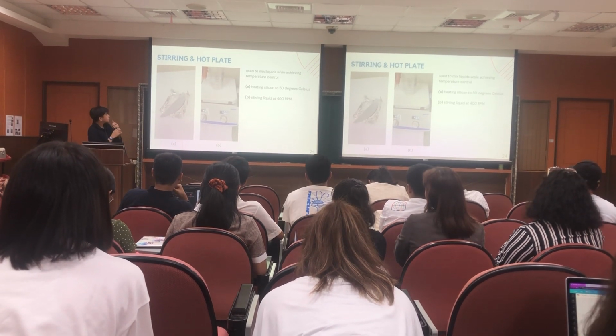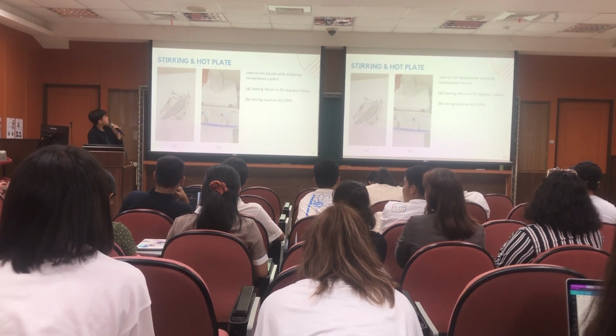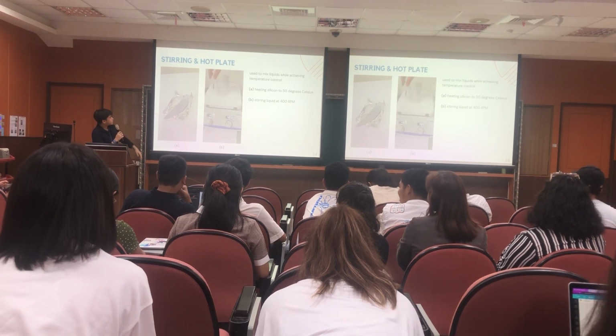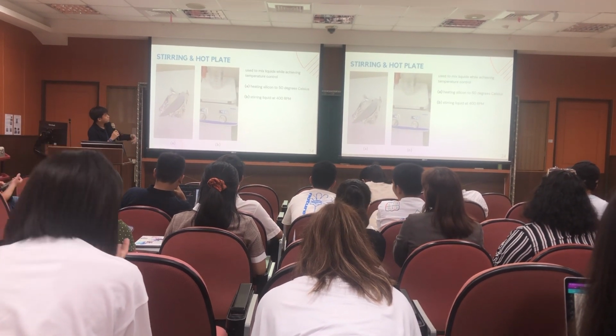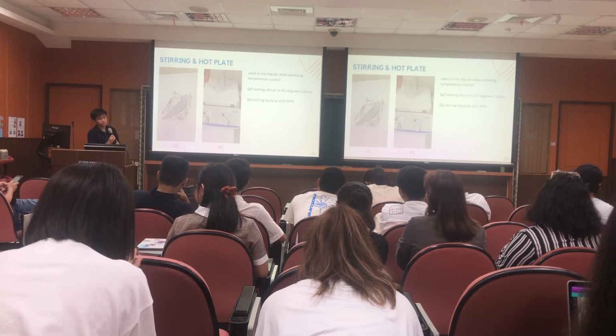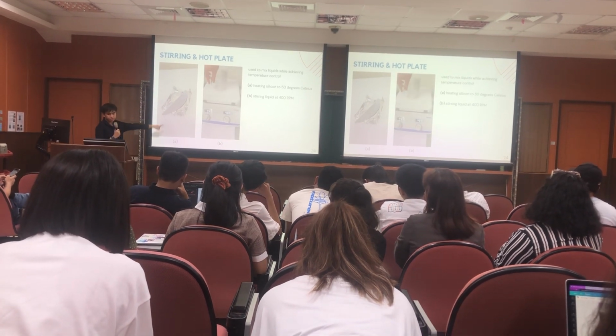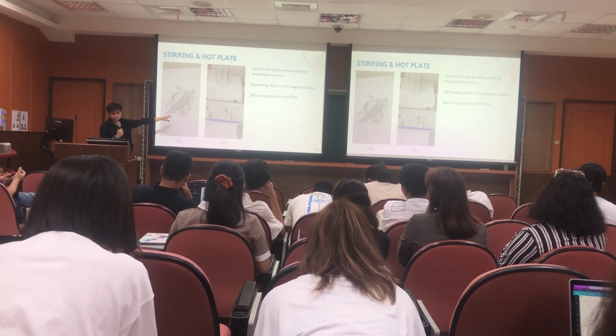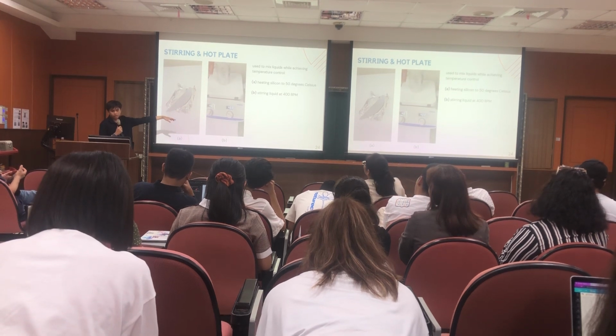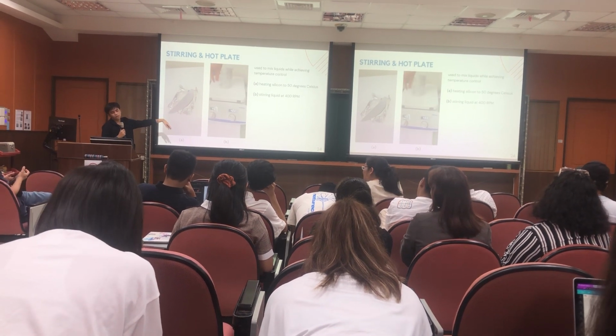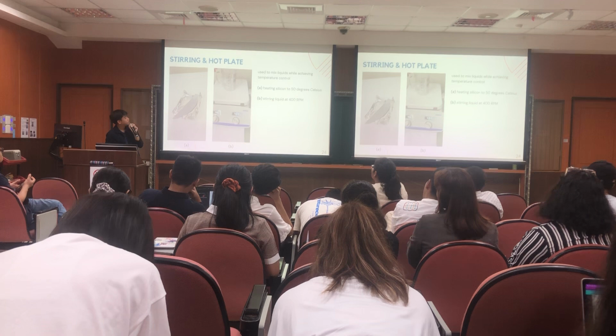The next piece of equipment that I want to talk about is your hot plate, which is multifunctional because you can use it to mix liquids while achieving temperature control. So in the first picture, we're heating silicon to 50 degrees Celsius to dry it from the water that we put on it. And in the second, we stir the liquid at 400 rotations per minute.